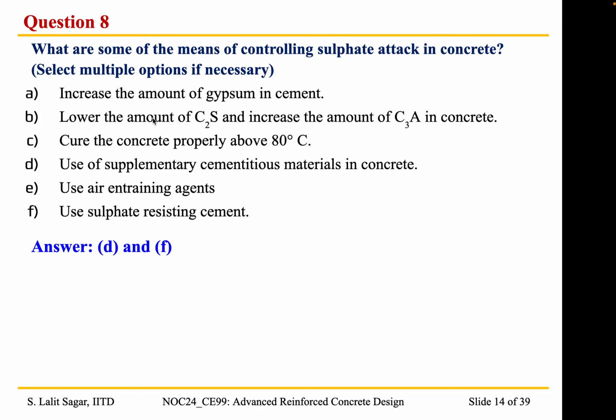as one of the participants very rightly mentioned, we have to increase the value of C2S because of the low heat of hydration, and we have to reduce the value of C3A because it has a high heat of hydration. Then, as we mentioned in the previous class, we need to cure the concrete at temperatures below 50 to 65 degrees, because curing them at high temperatures leads to delayed ettringite formation. And use of supplementary cementitious materials is not only useful in mitigating the effects of alkali silica reaction, but also effective in controlling the sulfate attack to some extent.